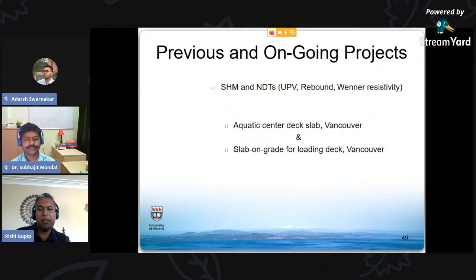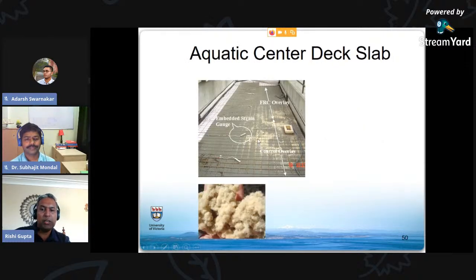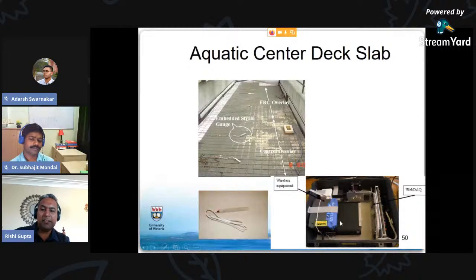So this is during my time at the University of British Columbia. So there are 2 projects that I wanted to show you. So this is a project where half of the slab had no fibers. The other half was actually fiber reinforced concrete, where cellulose fibers were being used. And we were monitoring using embedded sensors. So what you see here is embedded strain gauges that were placed at strategic points. We were interested in finding out the plastic shrinkage that takes place during the first few days in the pavement. This is back in the day.